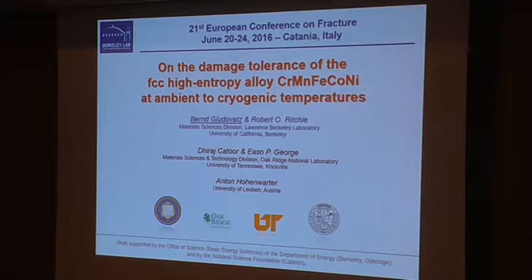For the specific microstructure, we had to, of course, also measure the mechanical properties, now only from room temperature to liquid nitrogen temperature. We found an increase in yield strength from 400 to 760 MPa, tensile strength from 760 to 1300 MPa, and the failure strain increased from 0.6 to 0.7, which is basically a 25% increase in failure strain, 70% in tensile strength, and 85% increase in yield strength. The strain hardening exponent was measured to be about 0.4, constant.